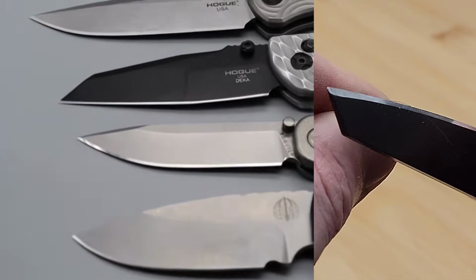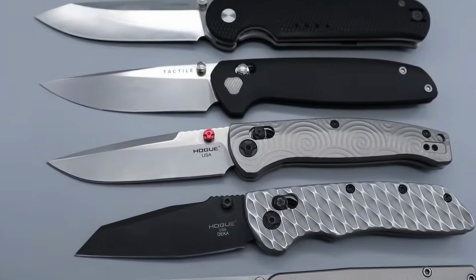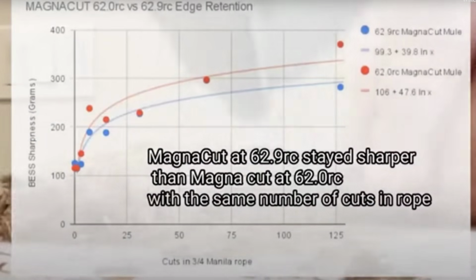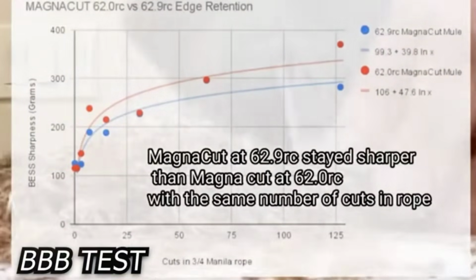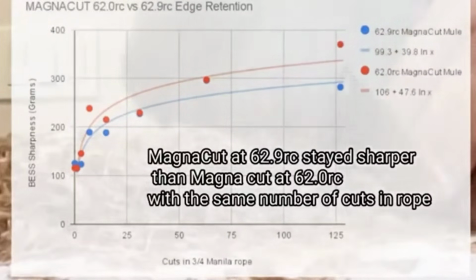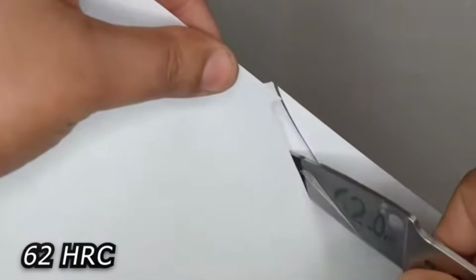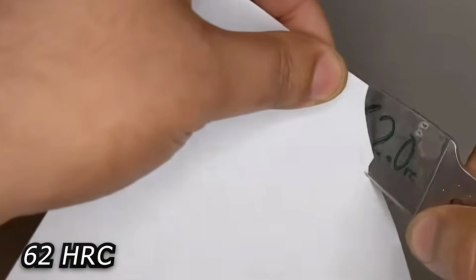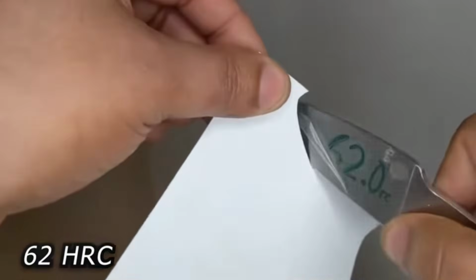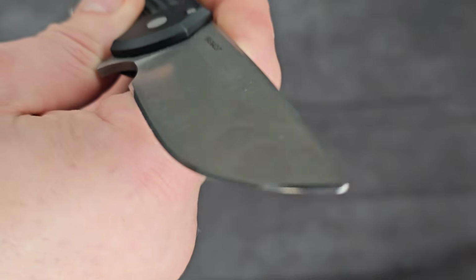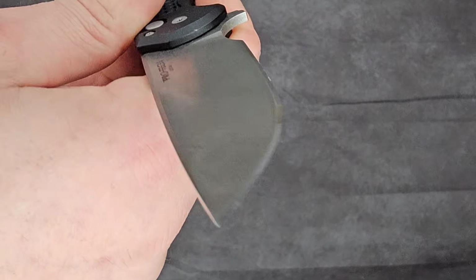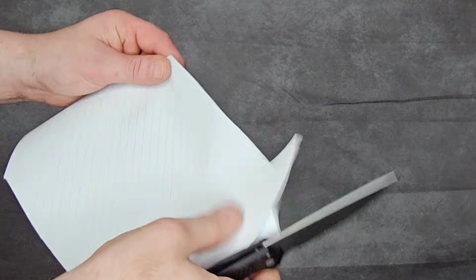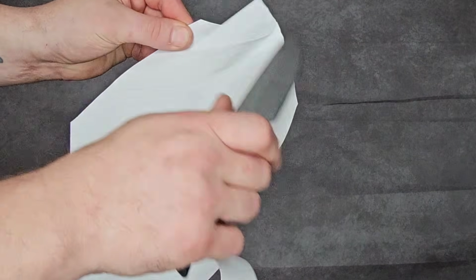Now, Magna Cut steel, like many other steels, most steels I should say, if not all steels, it's going to be highly dependent on the HRC of what type of finish you should put on it. If it's heat treated between like 63, 64 plus HRC, even the mid to higher side is 62 plus HRC, it will take great low angle polished edges and hold it extremely well with an insane amount of bite. It gets very sharp. It's a great steel to work with. However, when you get it to the lower side of the HRC, it's not going to do very well with the polished edge, and in that case you're going to want more of a medium grit edge, 600 to 1200 grit.